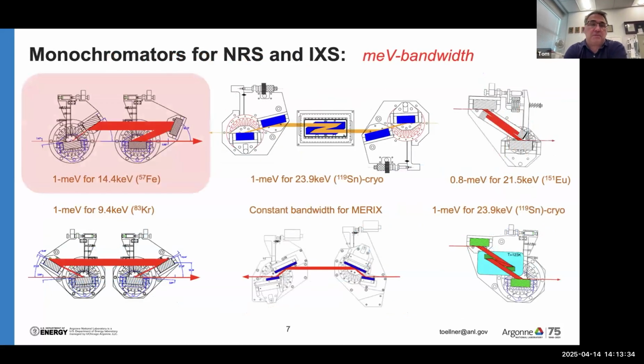These are just some of the monochromators that are used. The one in the upper left-hand corner is what is used for the iron resonance. All of these involve silicon crystals that are configured in a way to introduce a lot of dispersion and then remove that dispersion, preferably, in order to achieve a 1 meV bandpass. 1 meV is about an order of magnitude better than what you can do with just single crystals by themselves at this energy. And so it's a way of getting past that crystal back reflection limit in energy bandwidth.